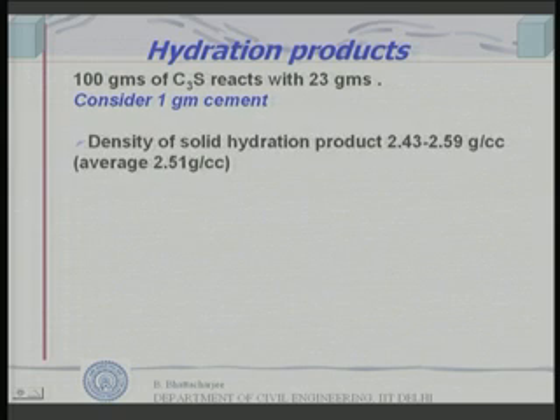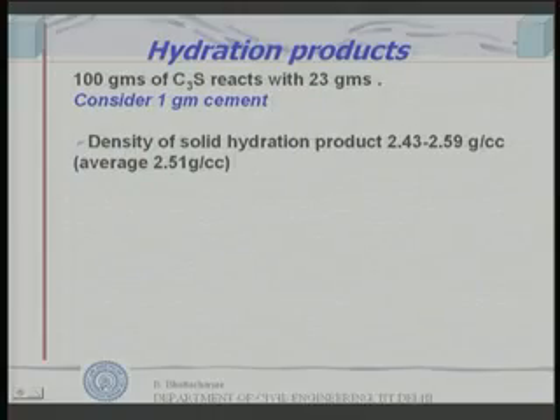We said 100 grams of cement reacts with 23 grams of water. Now, let us consider 1 gram of cement. Density of solid hydration products have been experimentally found to be 2.43 to 2.59 grams per cc. In CGS units, experimentally it has been observed the solid product of hydration that is formed has got a density of 2.43 to 2.59 grams per cc. So, one can assume average density is about 2.51 grams per cc.